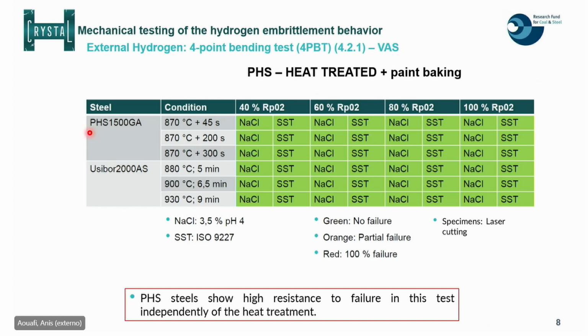And as you can see here, the result obtained in immersion in salt water or SST for different applied loads. So we vary the load from 100% of yield strength down to 40% of yield strength. And both materials don't foresee any crack. No failure has been observed using this test in this condition, independently of the heat treatment.